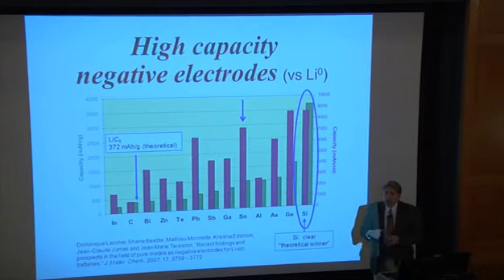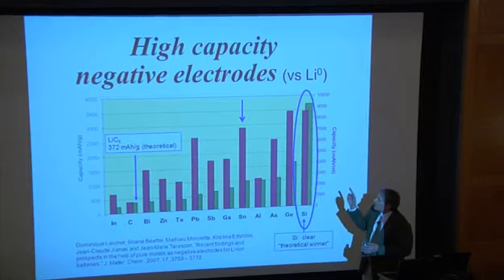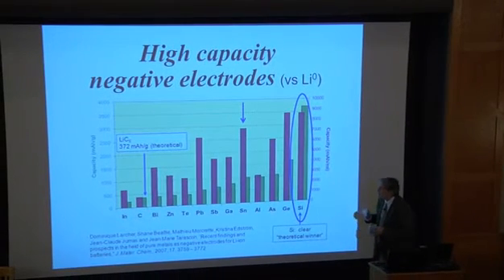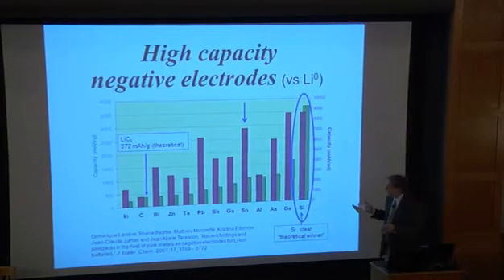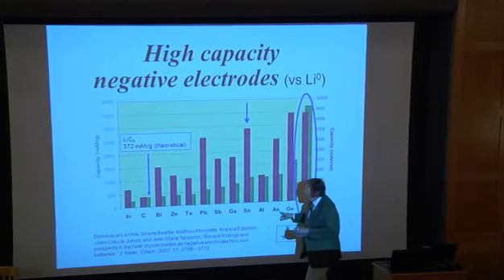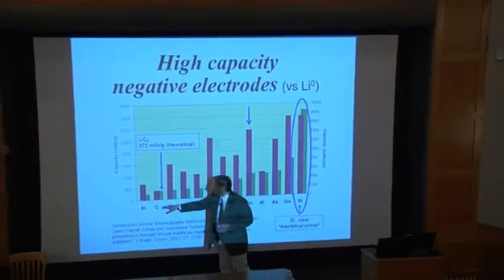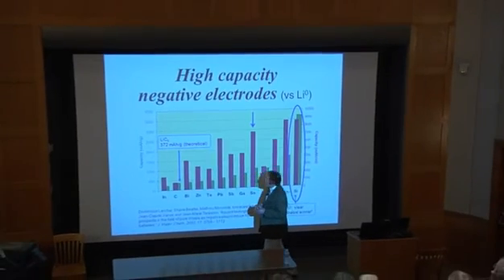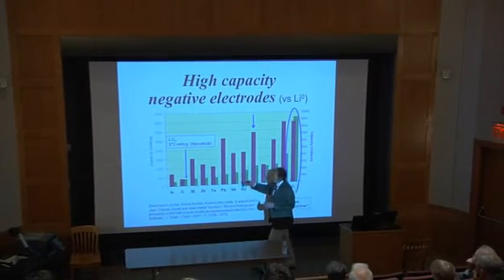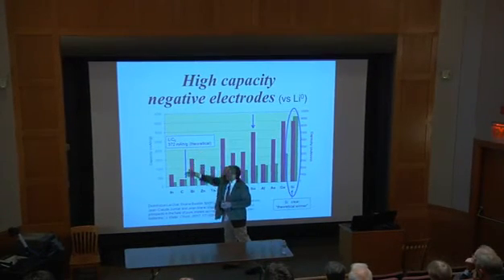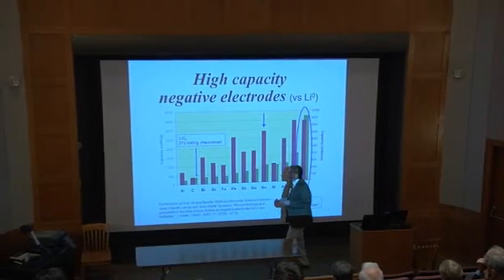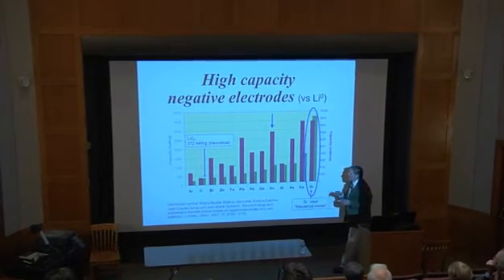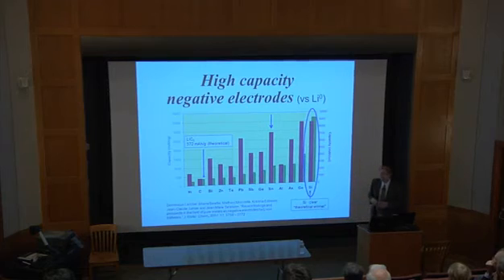So going on now more into the Gen 3, the reason there's a motivation to look at these systems, obviously, is high energy density. If you look at all the elements in terms of negative electrodes for materials, we're out here at about, theoretically, 372 milliamp hours per gram of host carbon for the current technology. Real systems get about 320 to 340 milliamp hours per gram. Silicon just blows it away.